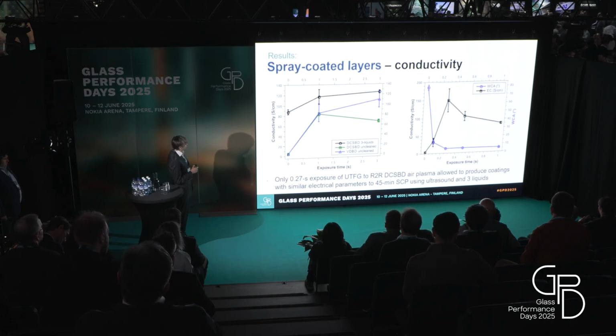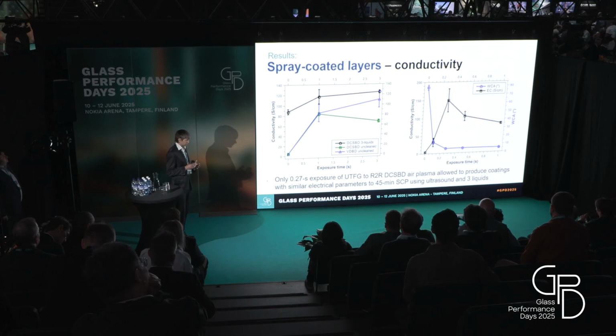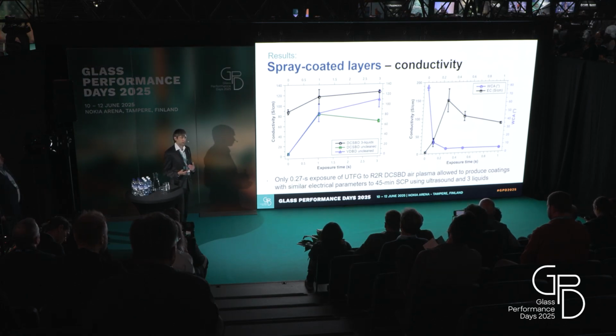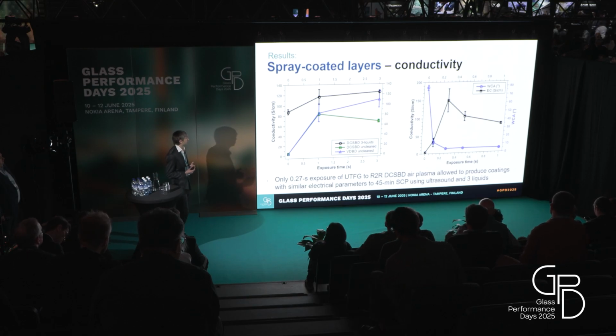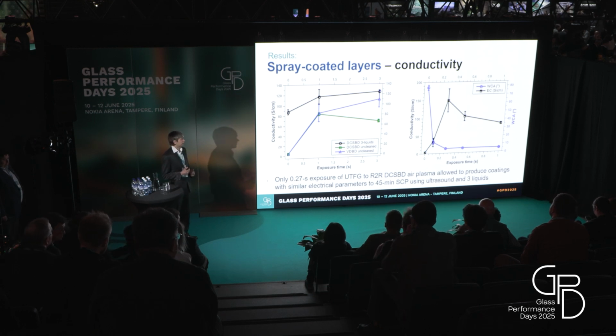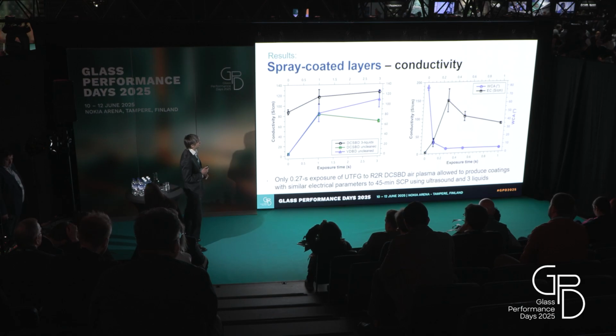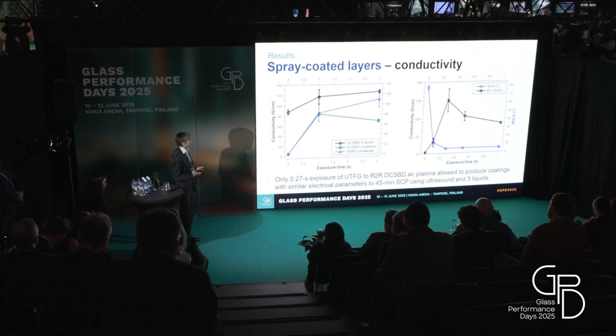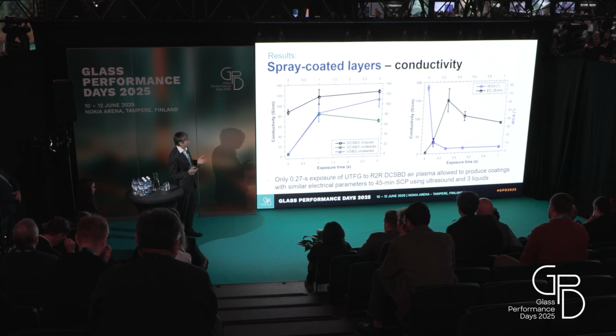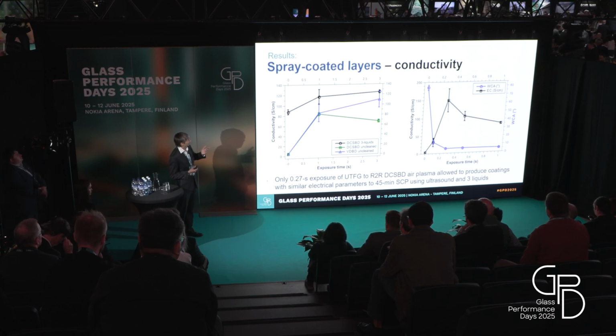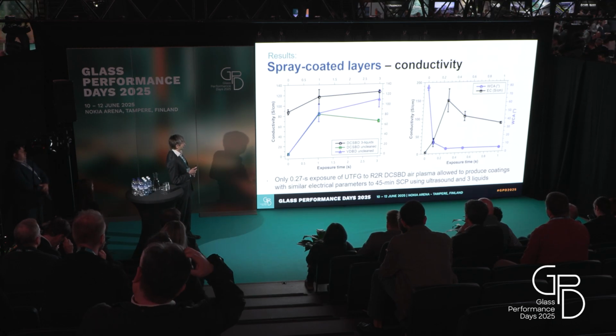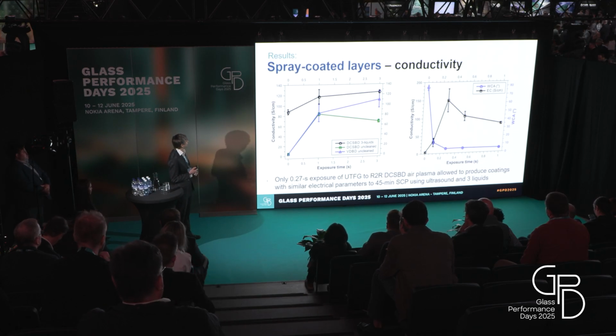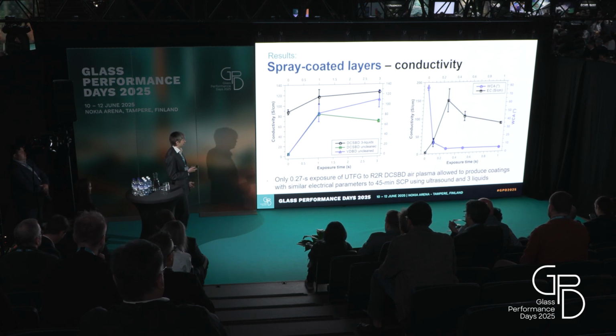And the spray-coated samples are done with the airbrush, so I needed to evaluate sheet resistance and thickness of these coatings because it varied more. So this is the graph of conductivity. And the conductivity also showed that the shorter treatment time increased the conductivity of our PEDOT:PSS coating. So here we can see that even 1/4 of a second is sufficient to increase the conductivity from a practically unconductive coating on the uncleaned flexible glass to very high values, which are very similar to the values of samples cleaned with the solvent cleaning protocol, which is also due to the uniformity of the coating.